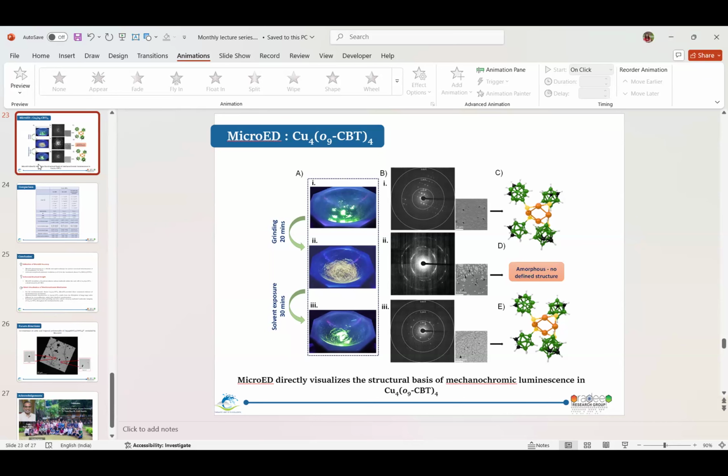Harshita, you are giving solvent vapor, right? Not the whole solvent. Yes, correct. That vapor won't be enough for reorganization to regain long range order from a short range order crystal. It's like you are telling that you are growing a large crystal from a small crystal. That cannot be happening. That is not physically possible. So you have to tune the explanation in a different way. This is not possible. Okay.